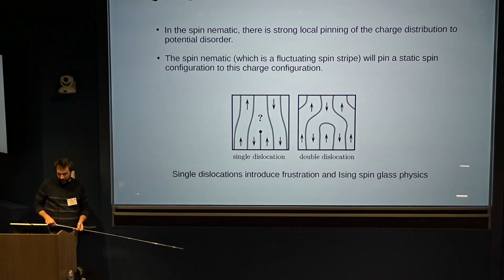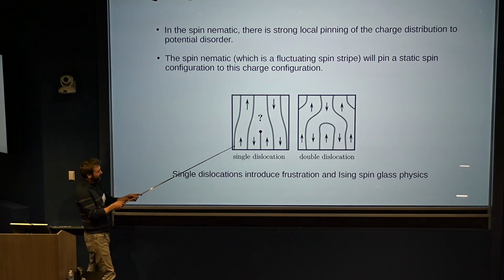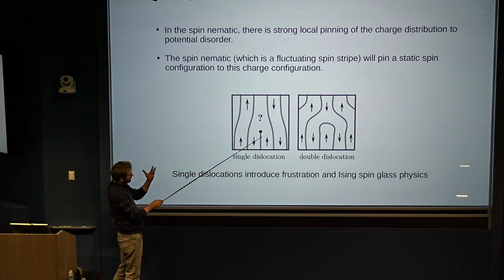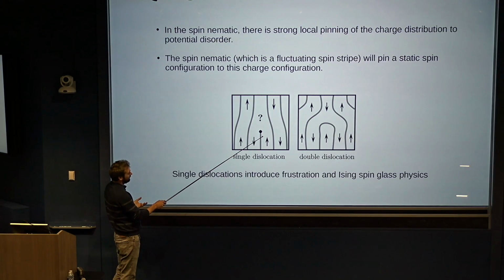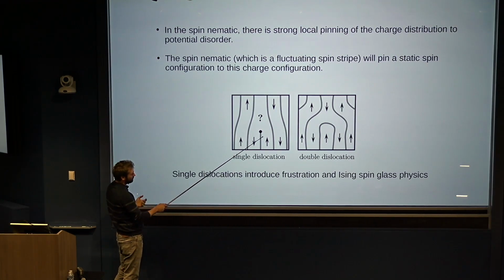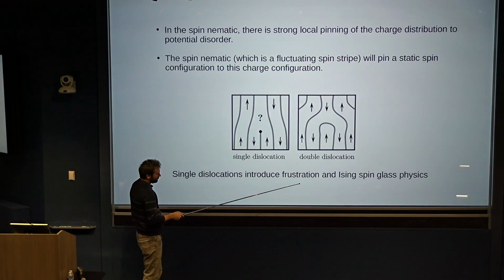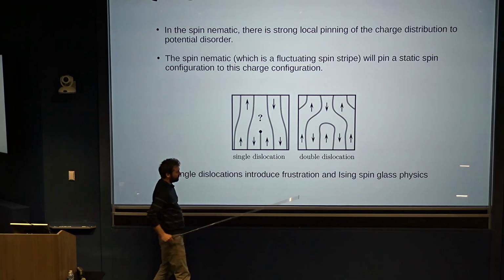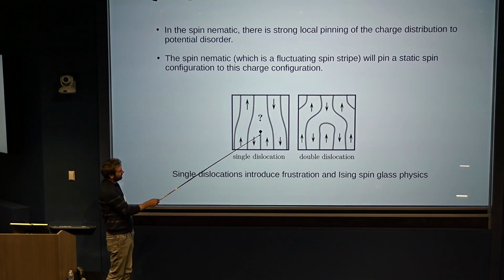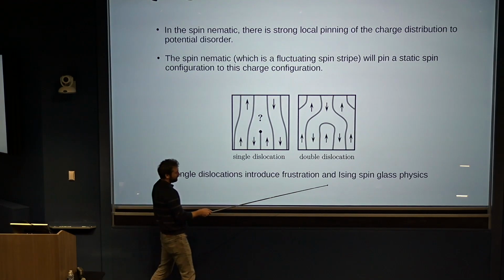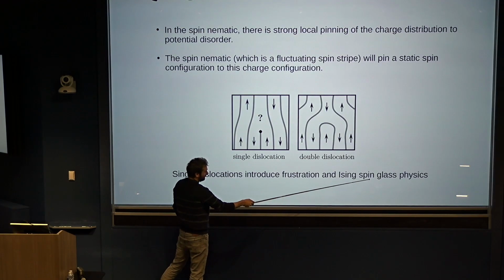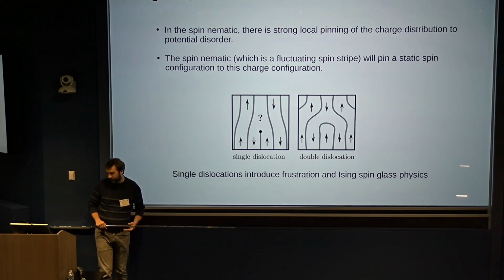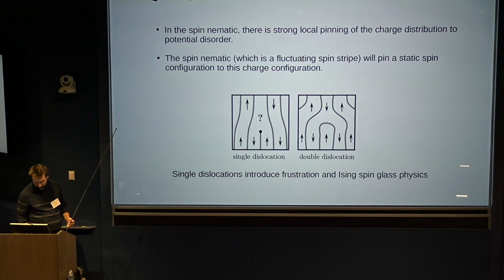Okay, so basically this type of frustration manifests itself in the Landau-Ginzburg theory such that if you keep the low energy configurations of your field, you find that part of your system reduces to an Ising spin glass Hamiltonian. So you find that these types of dislocations give rise to glassy Ising physics for the spins.